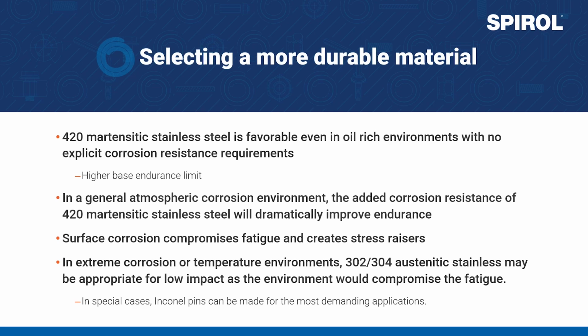A couple slides back, Mike was talking about the SN diagram that we have developed for the different materials of coil pins, where you could see a higher endurance limit of the 420 martensitic stainless steel. This is the favorable material for dynamic applications, even in environments where corrosion resistance is not of an explicit concern. Where there is a general atmospheric corrosion, the added benefit of corrosion resistance will prevent the surface from corroding and creating local stress raisers, which would compromise the service life.